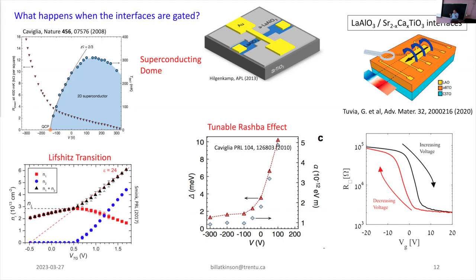Okay. The reason for this is that ferroelectricity, remember the model of the titanium rattling around in the cage, it was Coulomb interaction that was pulling the titanium off center. When you add free electrons, you're reducing the Coulomb interaction, you're just screening Coulomb interactions. So that's the picture of why ferroelectricity is suppressed. It's now been established that there are a number of materials where at least you get a window where the two can coexist. Okay, so I put this together as a way of showing you that a lot goes on at these interfaces and they're quite interesting.